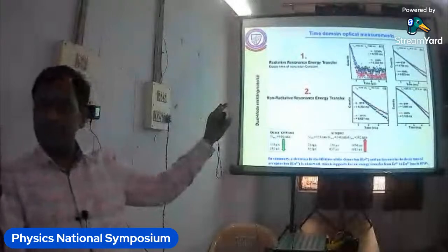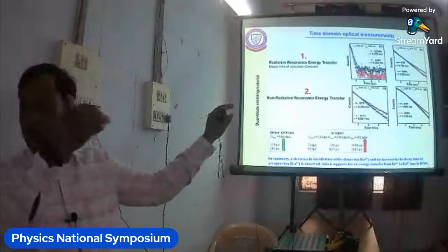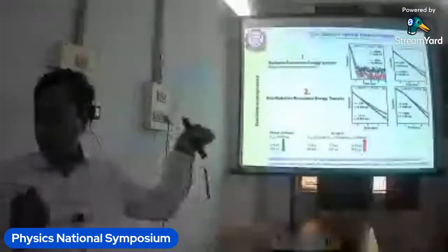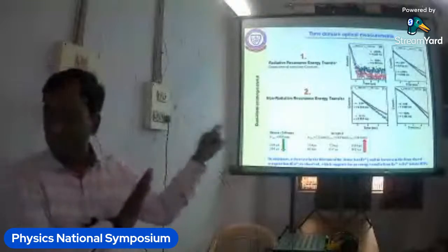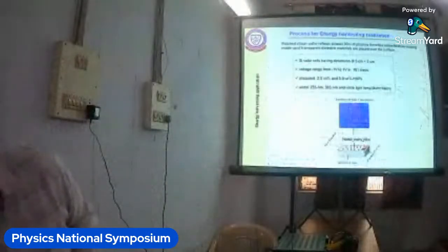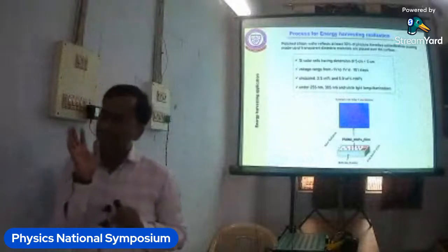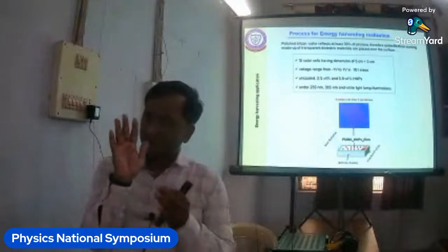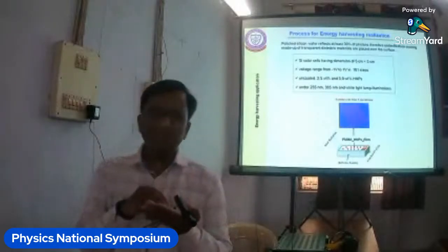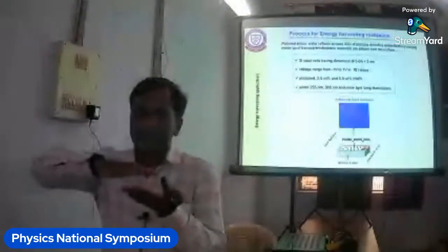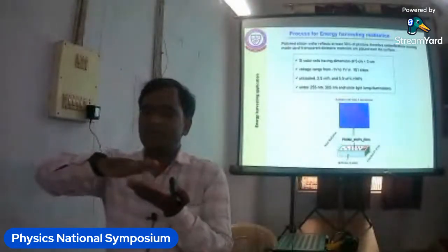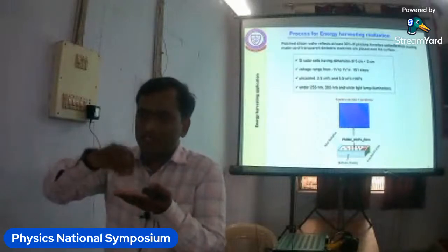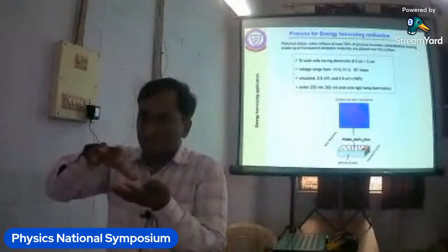So if erbium is giving its energy to europium 3+, in principle the lifetime of erbium 3+ would go down and the lifetime of europium 3+ would go up, and that we get. So by decay curve we also prove this. The last part that I want to convey is, the last question was, can this material be used for energy harvesting? So what we did, we dispersed this hybrid nanoparticle in a polymeric substrate, and this polymer was polymethyl methacrylate. So we are making a thin film which is loaded with our material, and the loading polymer is PMMA, which is transparent.